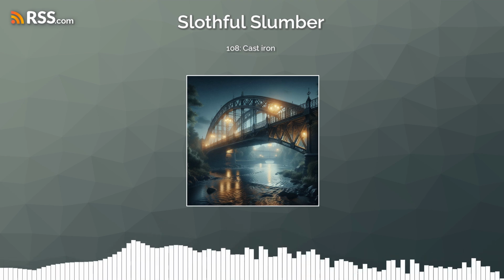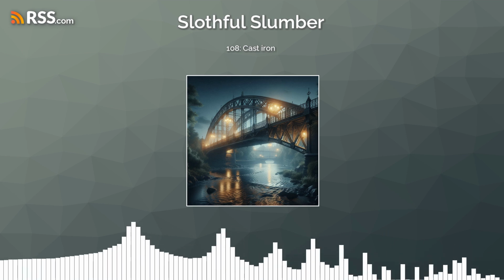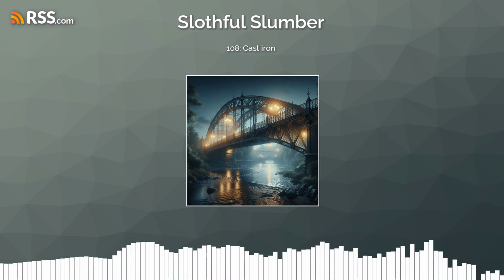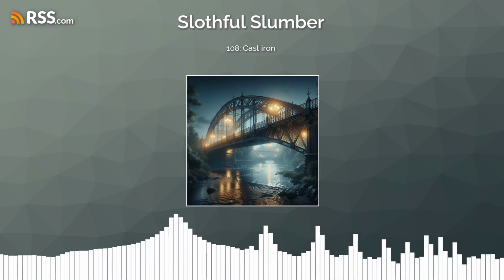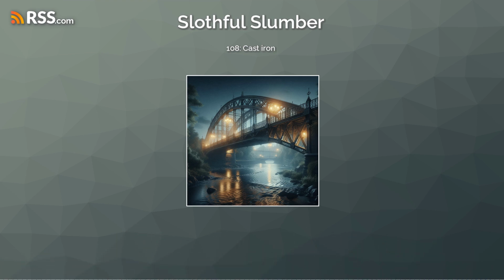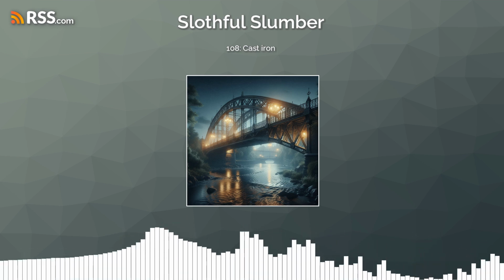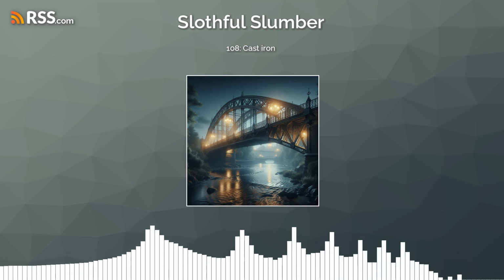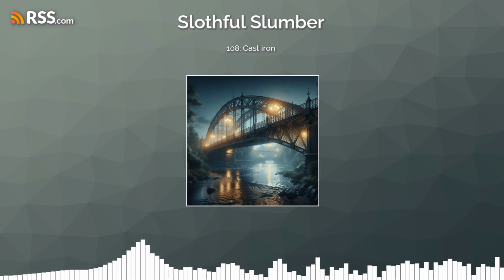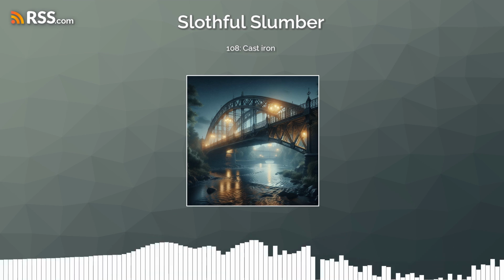Carbon as graphite produces a softer iron, reduces shrinkage, lowers strength, and decreases density. Sulfur, largely a contaminant when present, forms iron sulfide, which prevents the formation of graphite and increases hardness. Sulfur makes molten cast iron viscous, which causes defects. To counter the effects of sulfur, manganese is added, because the two form into manganese sulfide instead of iron sulfide. The manganese sulfide is lighter than the melt, so it tends to float out of the melt and into the slag. The amount of manganese required to neutralize sulfur is 1.7 times the sulfur content plus 0.3%. If more than this amount of manganese is added, then manganese carbide forms, which increases hardness and chilling, except in gray iron, where up to 1% of manganese increases strength and density.